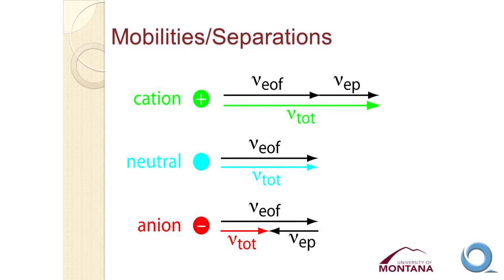And then in addition to that, we have an electrophoretic mechanism that we use to actually separate the compounds. And so cations, neutral compounds, anionic compounds all experience that same electroosmotic flow and are all transported by that flow. But cations have, in addition to that, an electrophoretic mobility in the same direction. And so they have a total velocity or a total flow movement, which is the sum of these two velocities. Anions have electrophoretic mobility in the opposite direction, and so they have a total velocity, which is the difference between the electroosmotic flow and the electrophoresis.